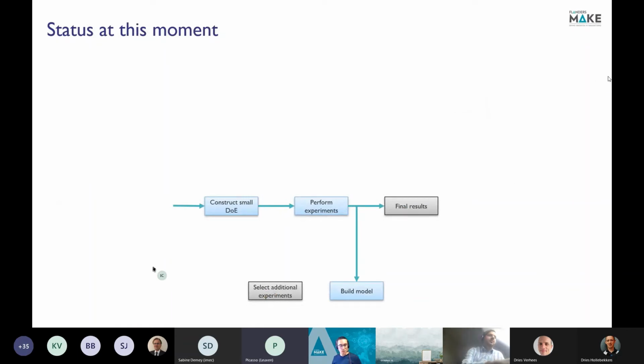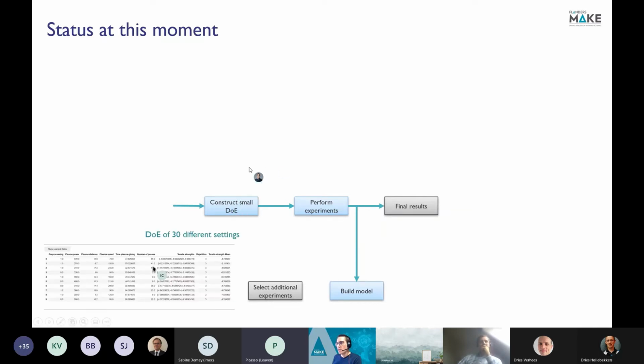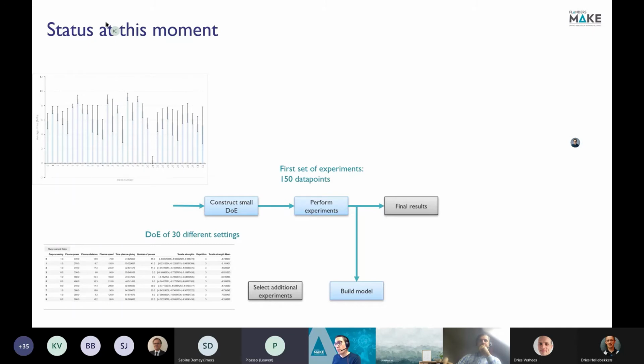Okay, so we tested this method now on simulations. And the idea that we also had is, okay, now we're starting also to check it on real life experiments where we really bond two pieces together and really perform the tensile test in the end. So what we did here was we first constructed a small design of experiments with 30 different parameter settings. Then we performed the real life validation experiments. In total, we did 150 data points.